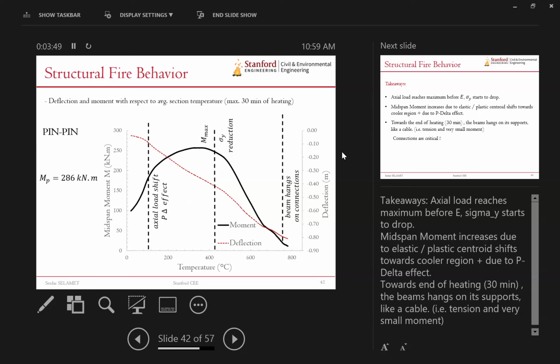When you look at the moment behavior at the midspan, you start with some moment in the beginning, right? Because it's loaded with 10 kilonewtons per meter uniform distributed load. The moment is counterclockwise, and it's actually getting higher. So you see this thermally induced moment counterclockwise higher up to a point where it reaches maximum. This increase is due to the shift of the axial load resultant that's acting on the centroid towards the cooler region. That adds additional moment to the beam at the midspan. You can think of this as not just the load shift, but also the P delta effect. Those two things act together to increase that shift outwards in the beam.